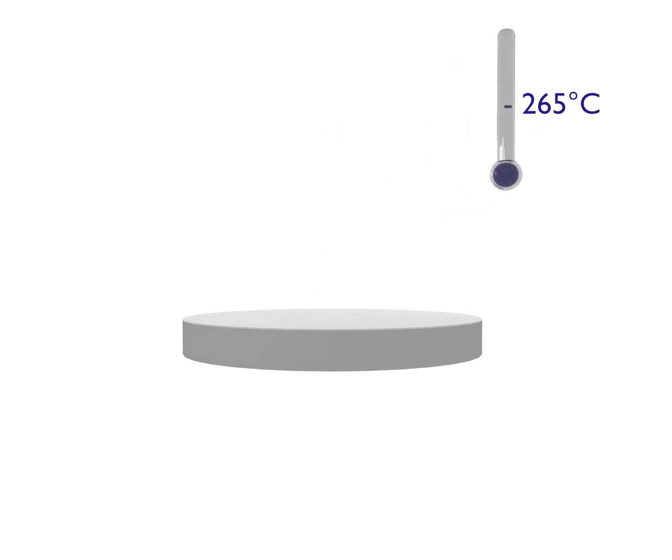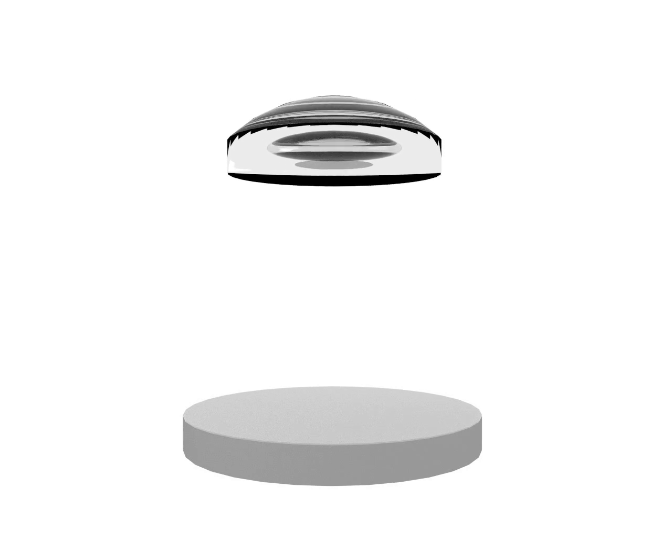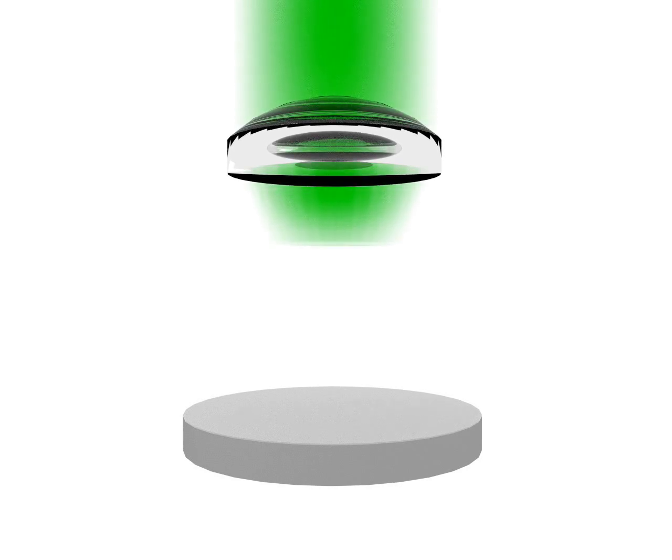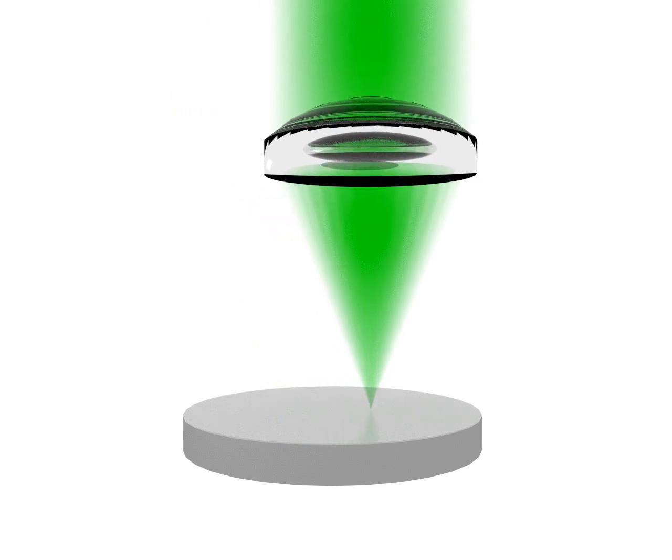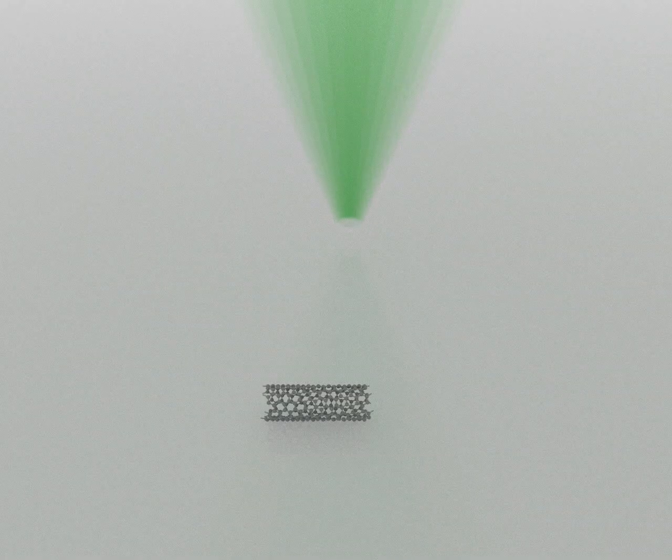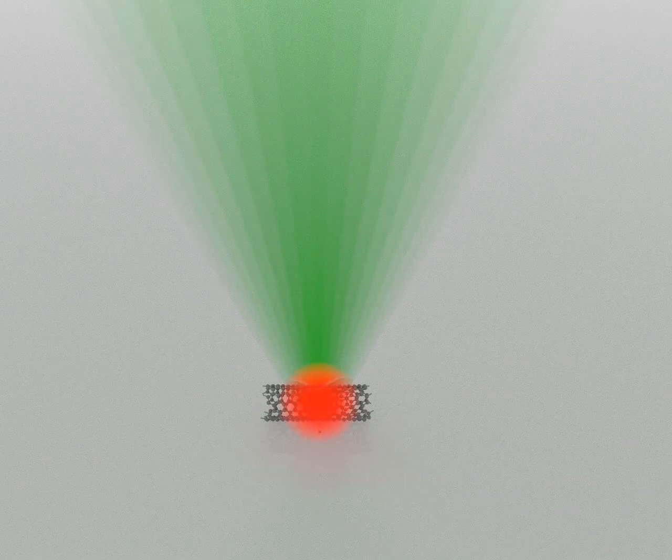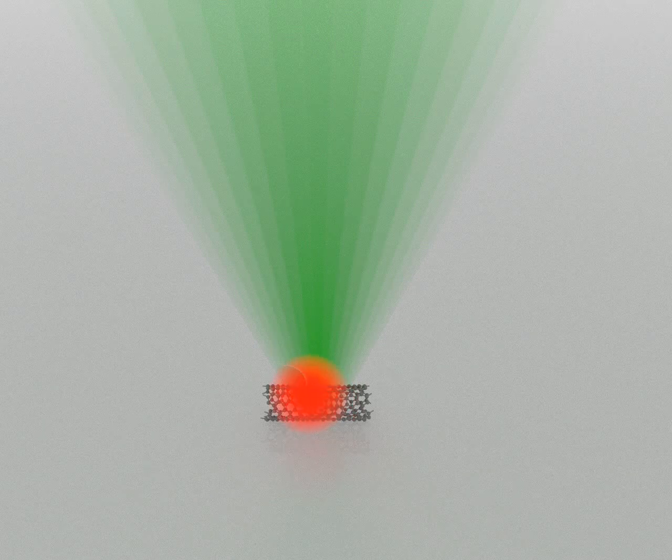But what's truly difficult is to find a nanotube on this mirror, because it's so tiny that it's invisible both to the eye and to an optical microscope. In order to locate it, we use a lens that focuses sharply light in a tiny point at the surface of a mirror. If we scan the mirror and if there is a carbon nanotube, it responds by emitting light of another color. So we detect a small red dot on the mirror, shining like a firefly in the night.